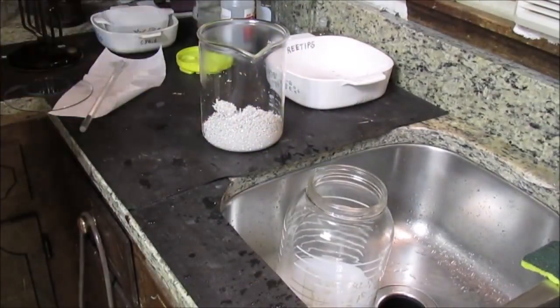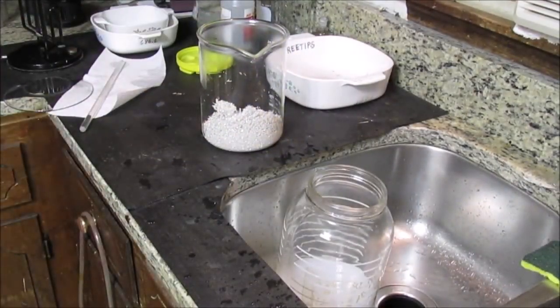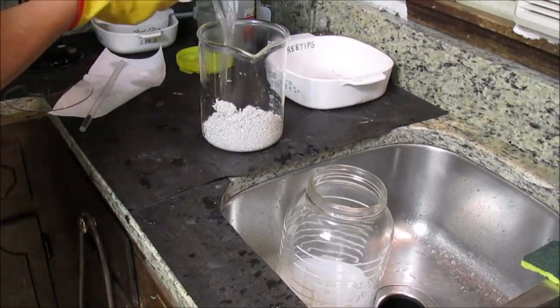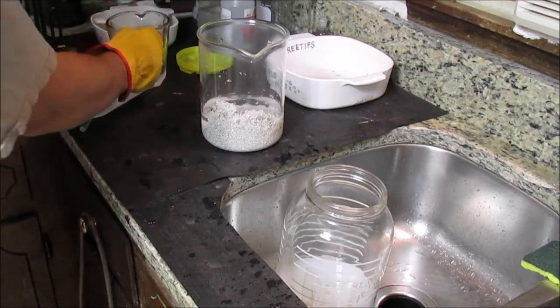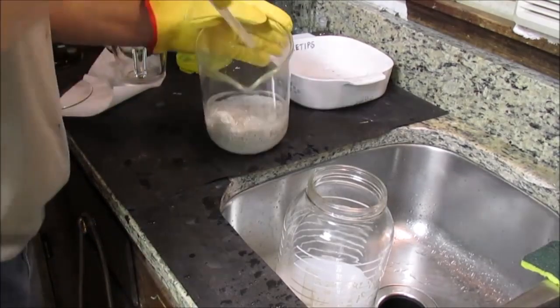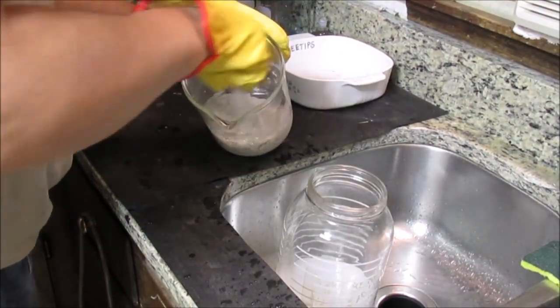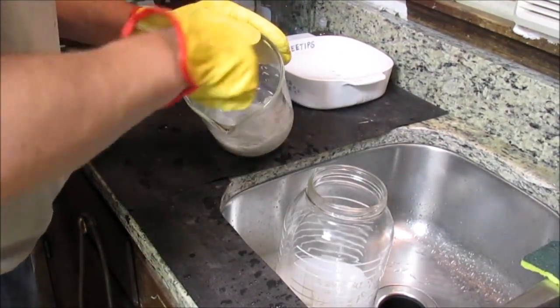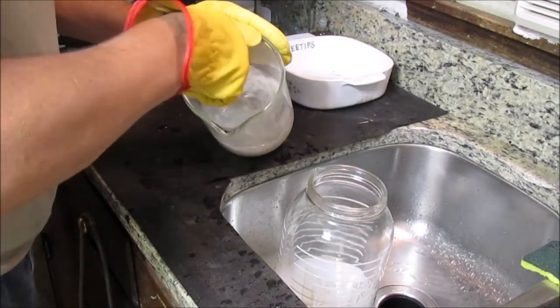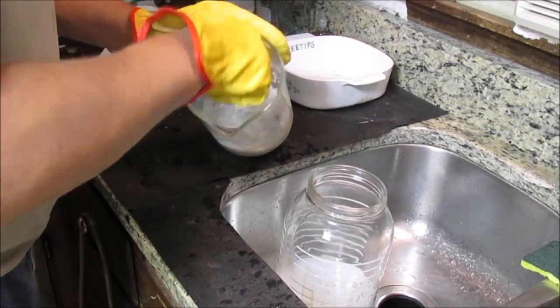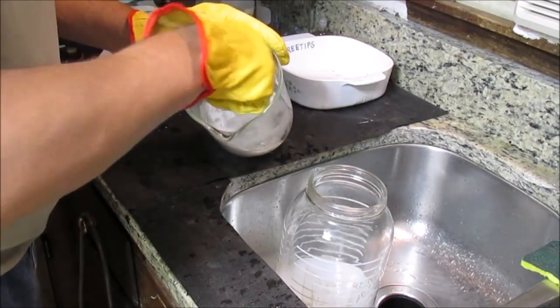Now I'm going to do a second rinse. Hot tap water here, about 180 degrees. No, hot distilled water, not tap water. This is distilled water, about 180 degrees. You can't use tap water here because it'll form silver chloride, something you want to try to avoid. So we're using hot distilled water to rinse these crystals off.